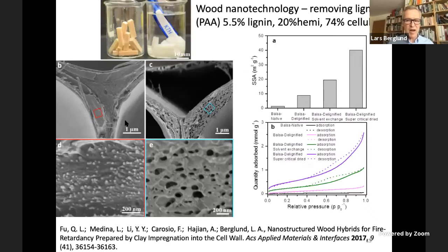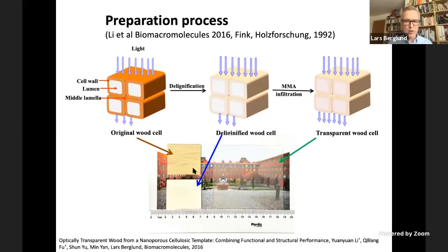And if you carry out this, if you look at the lower micrograph, this is a cell wall here. And if you look at it in very high magnification, you see cellulose fibrils in the lower left corner, and then you have the matrix of hemicelluloses and lignin. If you delignify, you change the color completely, it becomes white. We remove the lignin in the cell wall corners, and we also remove it inside the cell wall. So we create nanoporosity, which is of great interest for modification of materials, and we can get quite high specific surface area. And perhaps the most well-known example where we utilize this is in transparent wood.